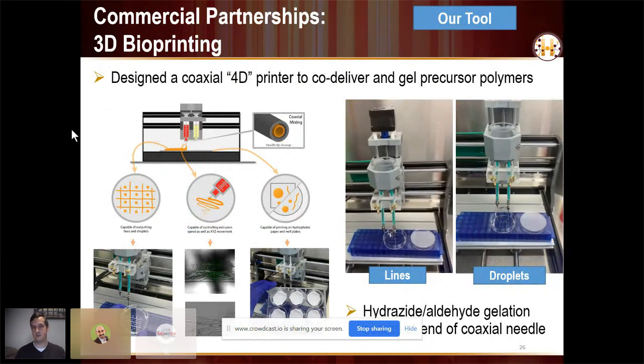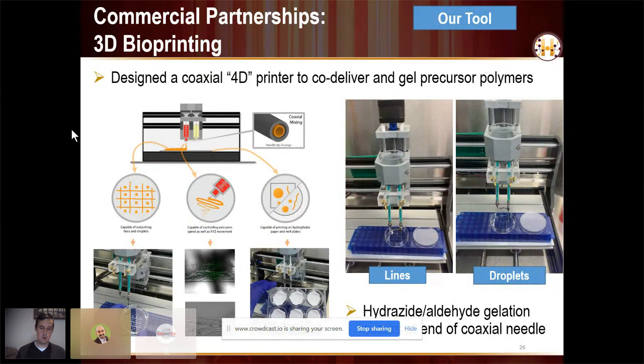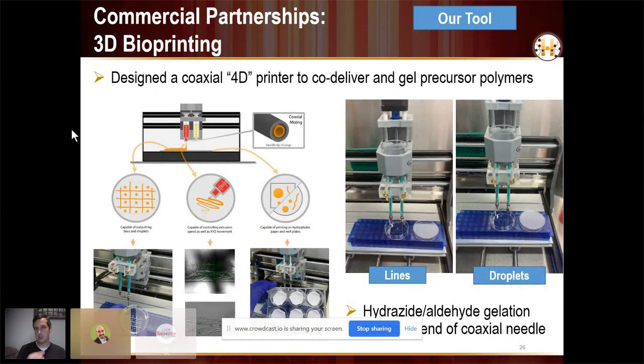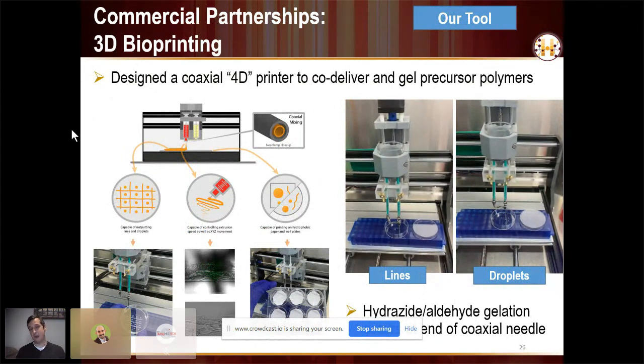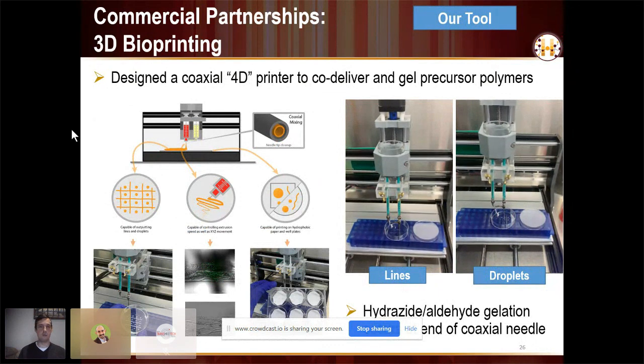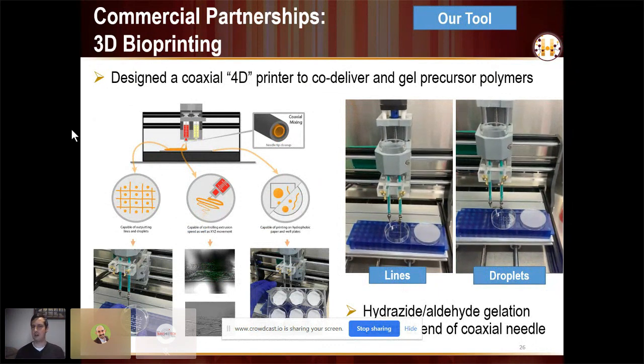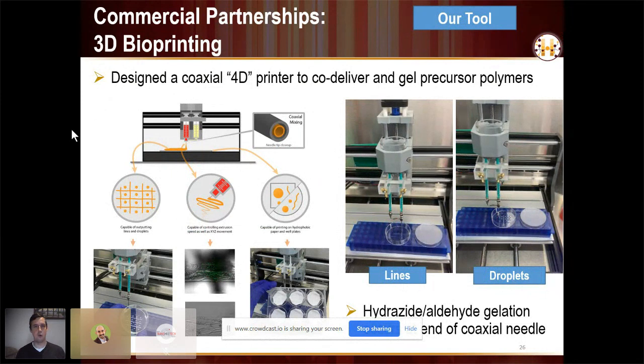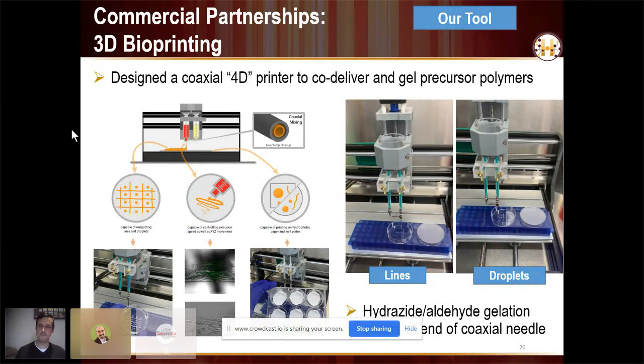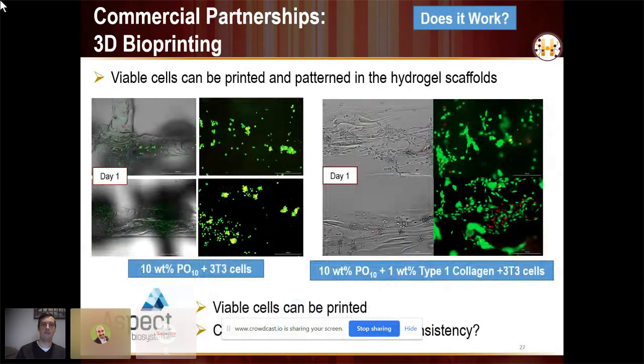The other thing we found is if we print on hydrophobic paper, we actually create almost discoid-like structures, which can almost match the size and morphology of red blood cells. And this is something we weren't expecting, and we're now quite interested in trying to pursue. Just to give you an idea, these are not fantastic images. This is still kind of early in this project, but you can see that cells can be printed.